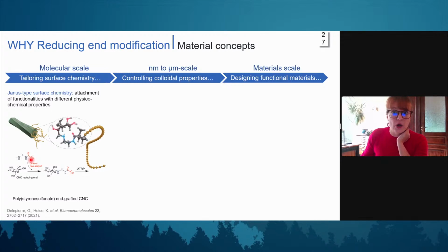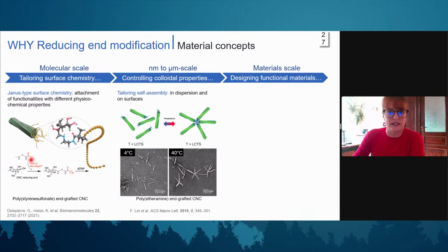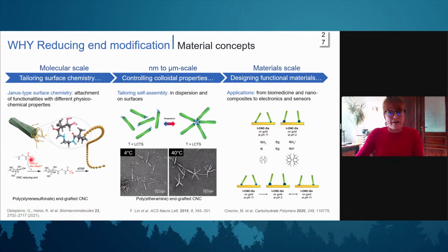Then in terms of controlling colloidal properties, there's a very interesting work, or several works actually, of Bruno Jean and his co-workers, and they have tailored self-assembly by grafting temperature responsive groups to the reducing end groups of cellulose nanocrystals, and above the lower critical solution temperature of the polymer, they have these nice star-shaped assemblies. And from the materials perspective, we have applications in composites, also electronics, and also in sensors. Sensors is more like the direction which is shown here. It's a relatively recent work of Chemin and co-workers. They have grafted pH responsive dendrimers to the reducing end groups and then assembled those on QCM sensors. And then they basically show by QCM the pH response. So really interesting concept for maybe sensor applications in the future.